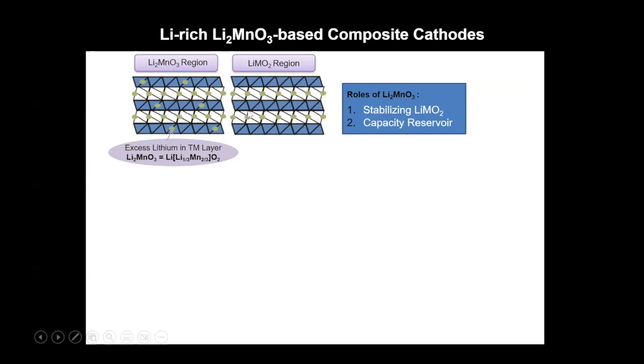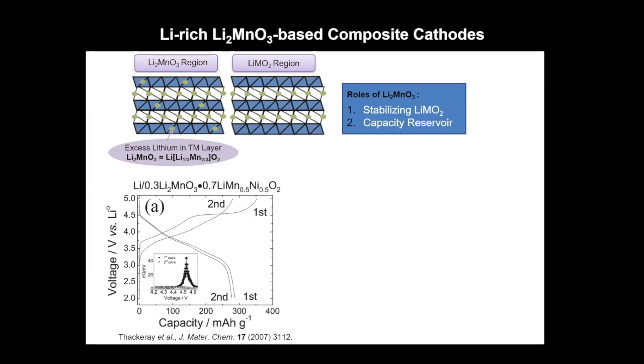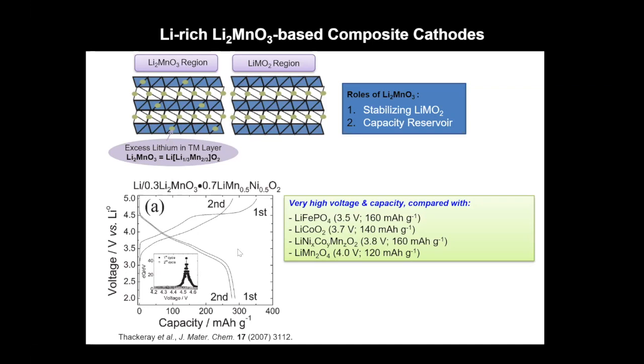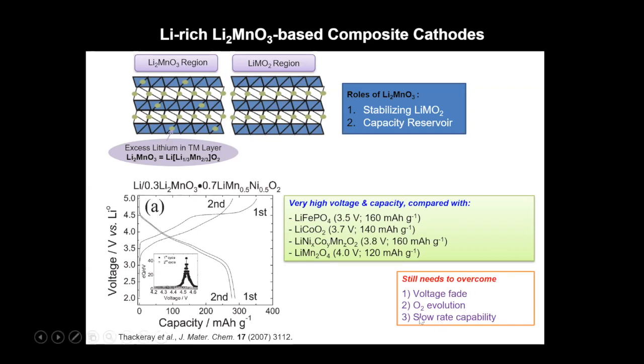The lithium-rich phase might serve two potential roles. One is as a stabilizing influence, that it can stabilize the layered phase during charge and discharge. And secondly, the lithium-rich phase, of course, contains a lot of lithium, and so it can serve as a capacity reservoir. So extra capacity can be obtained from this material. These are very famous materials discovered by Mike Thackeray and the Argonne group a long time ago. In general, they're pretty interesting because they have relatively high voltage and capacity compared to some other candidate electrode materials. But of course, they still have issues associated with things like voltage fade and oxygen loss and so forth.